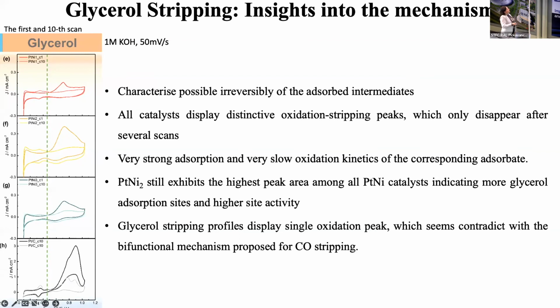You see that you could see oxidation stripping peaks. You see that the adsorption is very slow, so we know that the kinetics of the adsorbates are quite sluggish here. But again, you see that this exhibits the highest peak area among all the catalysts. And you could see that there is just one single peak compared to the CO stripping, which means that when we adsorb glycerol, probably we don't have a bifunctional mechanism.